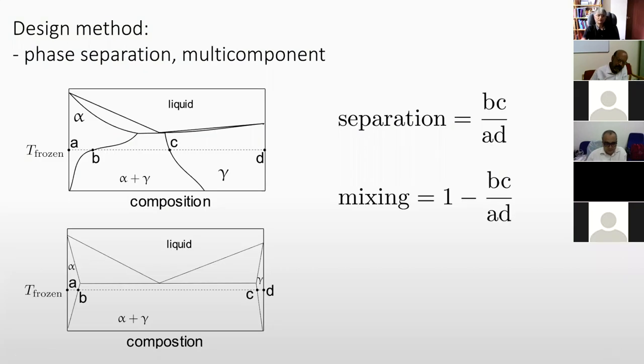Similarly, they looked at phase separation, where we are looking at the tendency for phase separation by looking at this distance here, BC divided by AD. And the tendency for mixing is, of course, the remainder, which is this segment and this segment. And those were also inputs into the machine learning. So with a phase diagram like this, there would be very little chance of getting mixing, but a very high chance of getting phase separation. But with a phase diagram like this, you might have a reasonable chance of getting mixing happening.